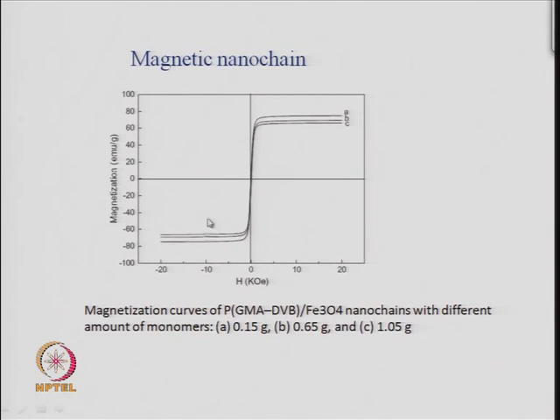There is no hysteresis, which one expects in a ferromagnetic material like iron Fe3O4, but Fe3O4 here is in very small size, nano sized, and hence it shows a super paramagnetic behavior. What is the difference in the three plots? The difference in these three plots is the amount of coating one has. Because you have added different amounts of monomers, the amount of coating has changed.